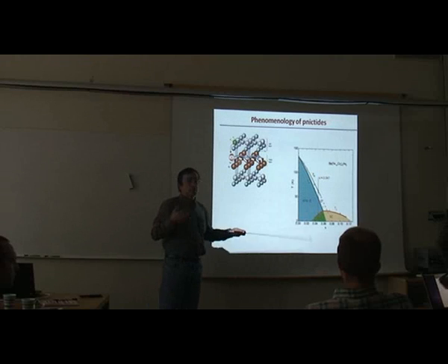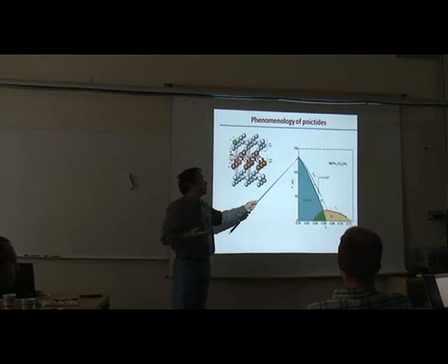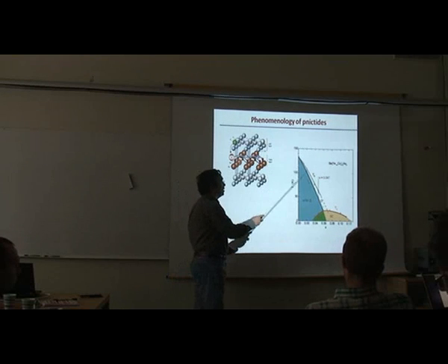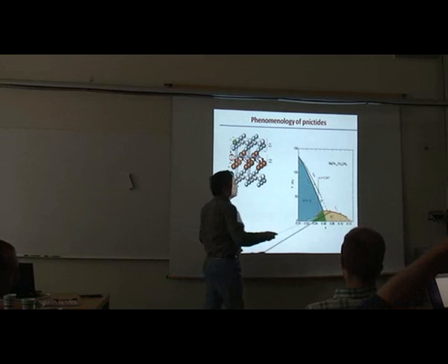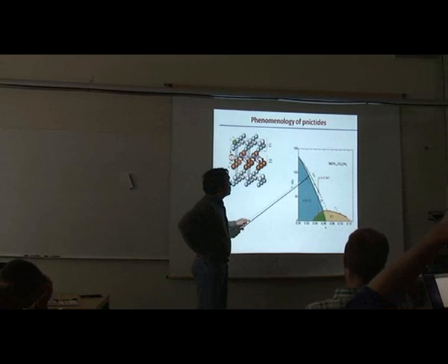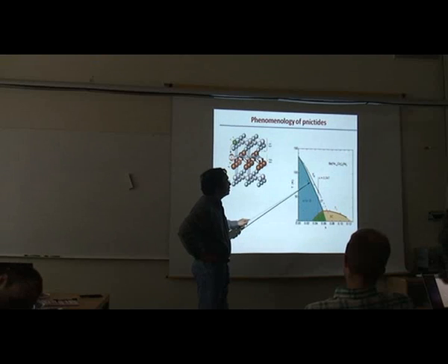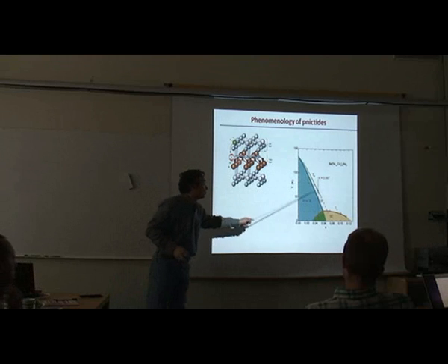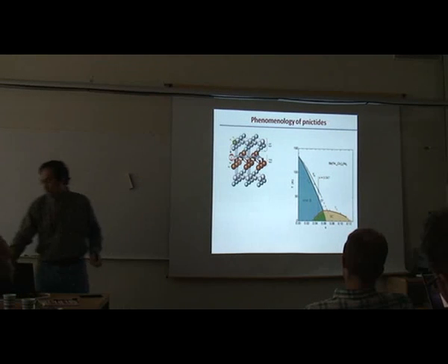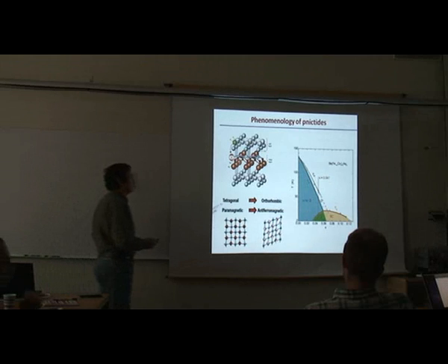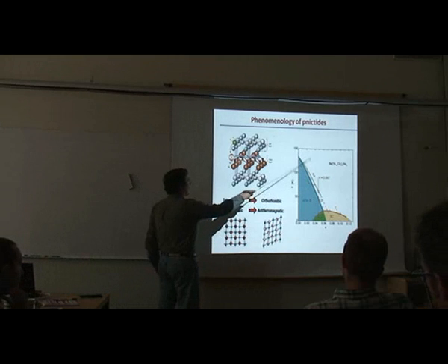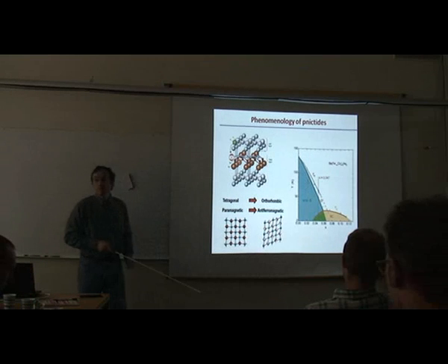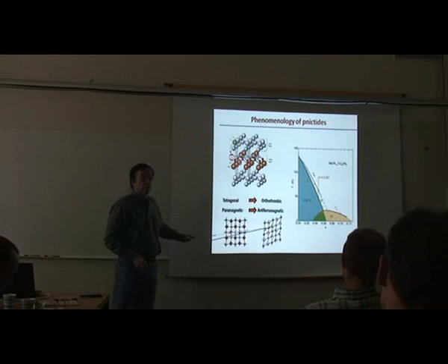So here, this material is a semi-metal, and then there's a spin density wave with a transition around 140 Kelvin. As you increase X, the Néel temperature drops, and then a superconducting dome emerges here. And also interesting that next to this antiferromagnetic transition, there's also a structural transition, very close. This line actually shows the temperature of the structural transition. And this structural transition looks like this. Here we have a tetragonal phase. As we cool down, it becomes orthorhombic and antiferromagnetic. So the structure goes from this to that.